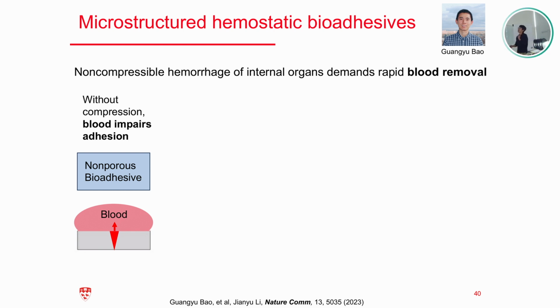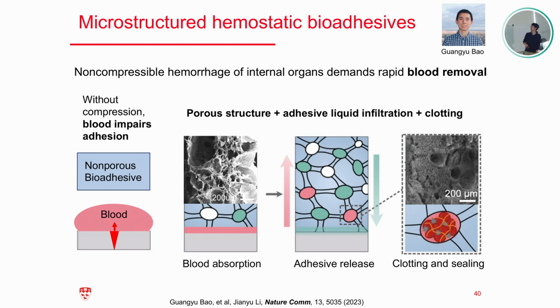But how we can remove that blood and form the adhesion is challenging for our previous generation 1 adhesive system. What we propose here is to engineer the structure of these adhesives, making it somewhat like a sponge. A sponge has a lot of pores, as you can see from our SEM imaging, on the order of 100 micrometers, and it allows this adhesive to actively absorb the blood on the surface, and at the same time, we can infiltrate some liquid adhesive into the matrix, which also enables the release of the adhesive polymer to enable adhesion.